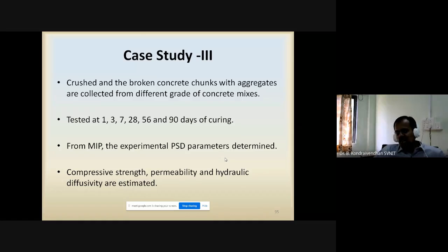So what he did, he used crushed concrete chunks for the different grades of concrete. He used PPC cement, and I think he has done three grades of concrete. He tested the concrete samples for 1, 3, 7, 28, 56, 90 days, and he determined the pore size distribution parameters. Using the pore parameters, he also calculated the compressive strength, permeability and hydraulic diffusivity. Okay, so that's what I am going to present.